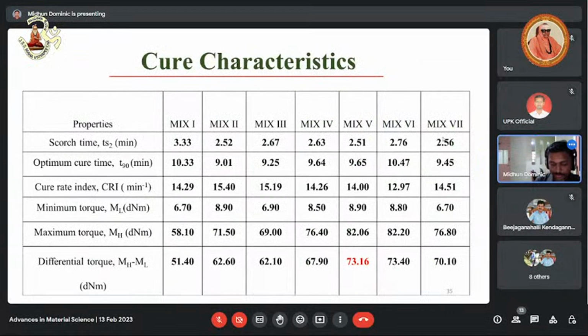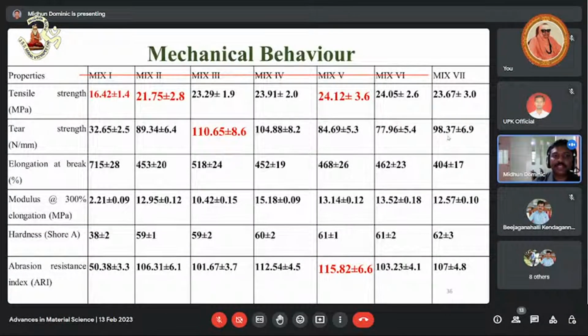And look at the results. Look at the tensile strength results. Mix 1, which has no carbon black and no chitin nanofiber, has a tensile strength of 16 megapascal. With carbon black 50 alone, tensile strength is 21. And if we use carbon black 50 and 1.5 phr of chitin nanofiber, tensile strength improved from 21 to 24.